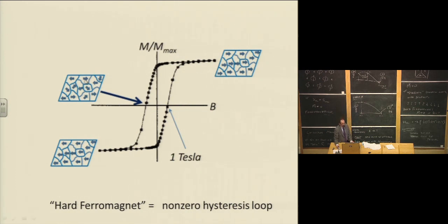The only difference is that with the crystallites, the domain walls are always between the crystallites, if you want to think of it that way. Some crystallites will point in one direction, some will point in the other direction, and to move the domain wall, you have to flip over one more crystallite. So it's extremely similar physics. The moral of the story is that in order to get a real magnet, a hard ferromagnet, somehow or other you have to have disorder in your system, whether it's making the system into small little crystallites or putting in disorder that's going to pin the position of the domain walls.